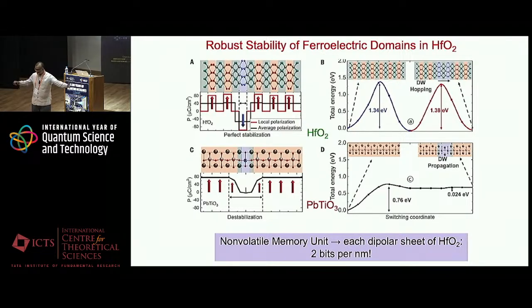So you have an infinitely degenerate ground state which is associated with any ordering of these dipolar directions of these two-dimensional sheets. This is contrasted with the conventional ferroelectric lead titanate, where if you try to switch one sheet of titanium atoms, it basically leads to an increase in the domain size and overall switching of the full sample. So the advantage of hafnium oxide is you can store memory in a single dipolar sheet shown here, which has about the same energy as the starting point.